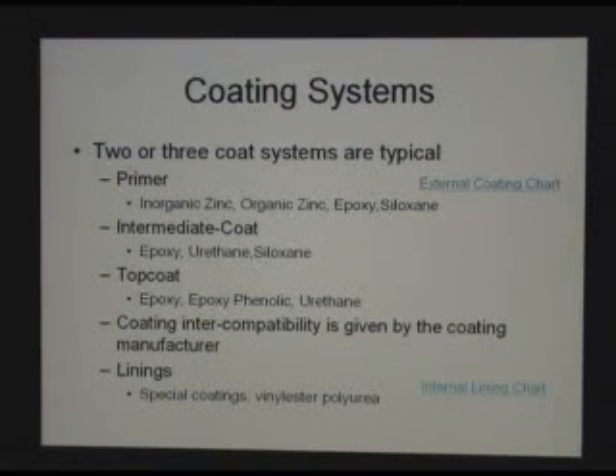Okay, the paints we arrange into coating systems, which is a multi-layer application of paint. Typically there's at least a primer and a top coat, but the preferred method is a primer, an intermediate coat, and a top coat. The top coat is mainly there to preserve the appearance of the coat, to keep it glossy. In this case, we use quite often urethanes, which have excellent resistance to UV, but also epoxies are used. All these systems are, of course, temperature dependent, so we have to make a system for each temperature range, and also quite often for location.